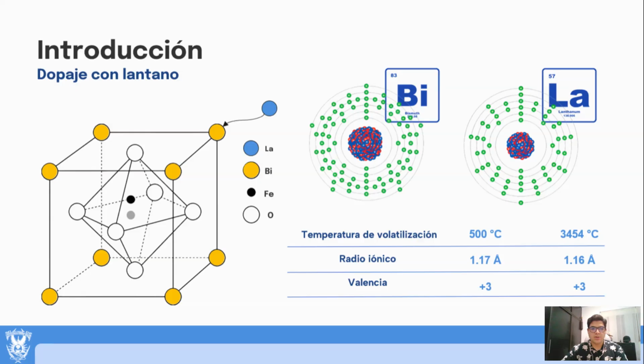First, it stabilizes the perovskite phase by suppressing secondary impurity formation. Second, it reduces charge carrier concentration by decreasing oxygen vacancies and bismuth-related defects. And third, it modulates magnetic properties by inducing lattice distortion that affects BFO's antiferromagnetic ordering. Studies have shown that compositions with 10% doping exhibit significant improvement in spontaneous polarization, along with reduced dielectric losses.